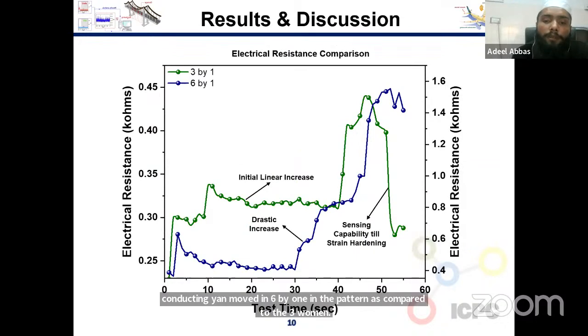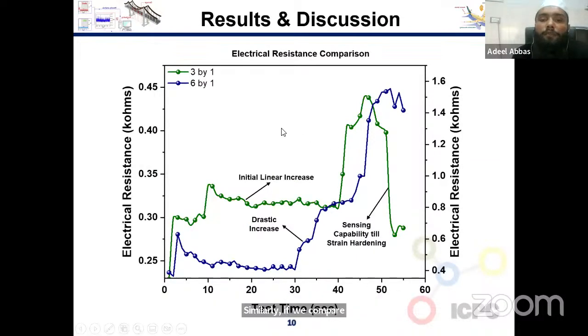Similarly, if we compare electrical resistance values of both 3x1 and 6x1 inlay patterns, we can clearly see that the electrical resistance of the 3x1 specimen is more linear as compared to the 6x1 specimen. As during the initial test time, there isn't any specific fluctuation in the electrical resistance, depicting that our 6x1 inlay pattern isn't capable of monitoring the health of the composite.